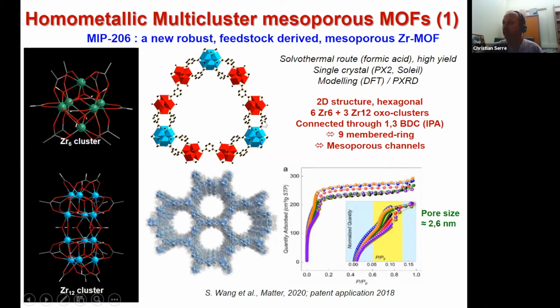we obtain this solid. The structure was solved on a protein beamline with a microfocus beam at the PX2 beamline at Soleil near Paris. Because the quality of the data was not so good, we had colleagues refine the structure by DFT, and it was further validated by high resolution X-ray diffraction. And so this material has a 2D structure. Here, it's a hexagonal structure.